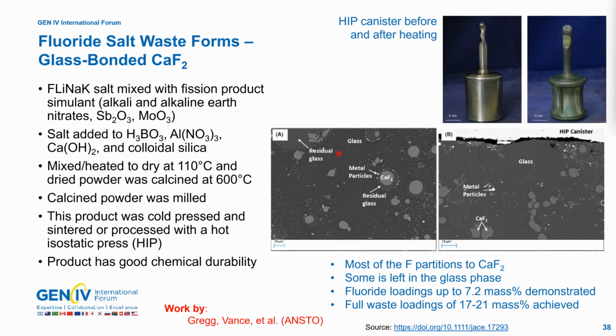They also found some residual fluorine present in the glass, and these materials had fluoride loadings up to 7.2 mass percent and full waste loadings of 17 to 21 mass percent. So this is a really neat idea to basically force the fluorine, which is known to be very difficult to immobilize, into a very nice, stable, chemically durable phase of calcium fluoride.